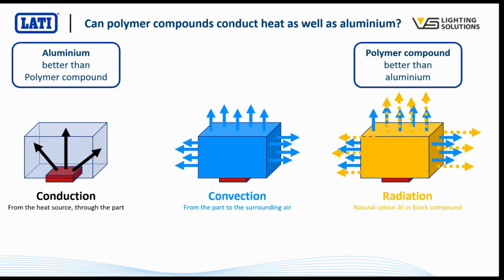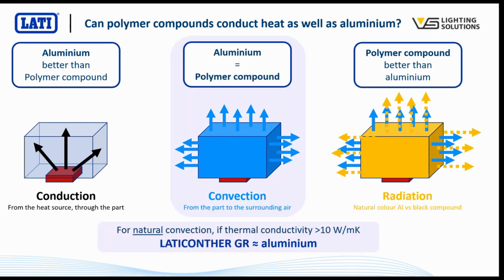We're wanting to take heat from the part and transfer it to the surrounding air. And what we find with this is that aluminium and polymer compounds behave very, very similarly, providing we have a thermal conductivity of around 10 watts per meter Kelvin or above. And as we saw with the previous slide, we comfortably meet that with the thermoplastic.